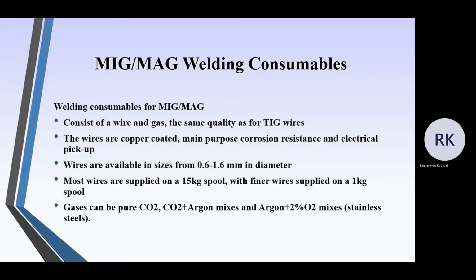Then MIG welding consumables. MIG welding consumables consist of wire and gas, of the same quality as TIG wires. The wires are copper coated again, and the main purpose is to resist corrosion and electrical pickup. Wires are available in sizes 0.6 to 1.6 mm in diameter. Most wires are supplied on a 15 kg spool, with finer wires also supplied on a 1 kg spool. So gases can be pure CO2, CO2 plus argon mix, or argon plus oxygen mix.